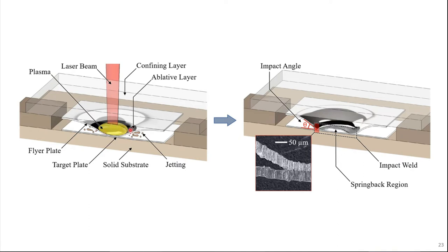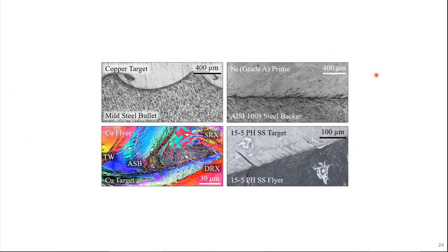You get your plasma which forms, and what you get is this sort of annulus weld which looks like what you see over here in this optical micrograph. You can also sometimes get this sort of spring back effect in the center. And just to give you an idea of what microstructure in impact welds have looked like through the decades, the images on top were taken in the 1960s, 1970s. The images at the bottom were taken somewhere in the last 5 years. In all cases, at the interface of the impact weld, you notice there is some change in the microstructure compared to further away from the interface.